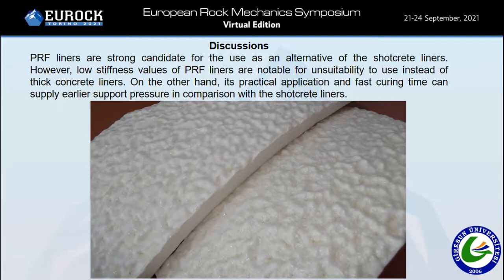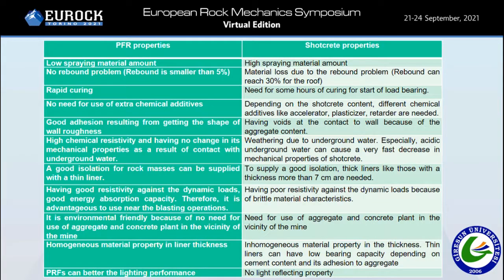However, low stiffness values of PRF liners are notable for unsuitability to use instead of thick shotcrete liners. On the other hand, its practical application and fast curing time can supply earlier support pressure in comparison with shotcrete liners. Because of its ductile material characteristics, PRF liners have a good energy absorbing capacity, which makes the liner supports advantageous against the dynamic loading. PRF material has significantly higher energy absorbing capacity in comparison with the shotcrete materials. Therefore, use of the PRF liners is profitable to combat the rock burst problem.